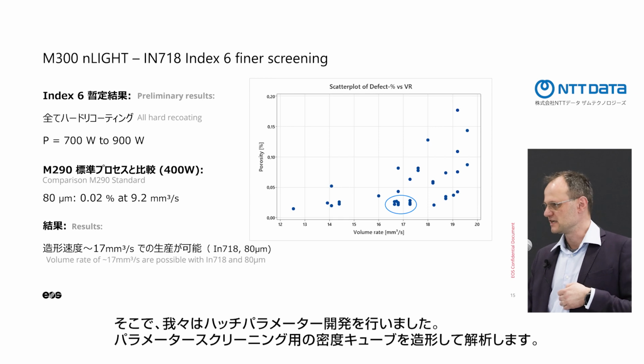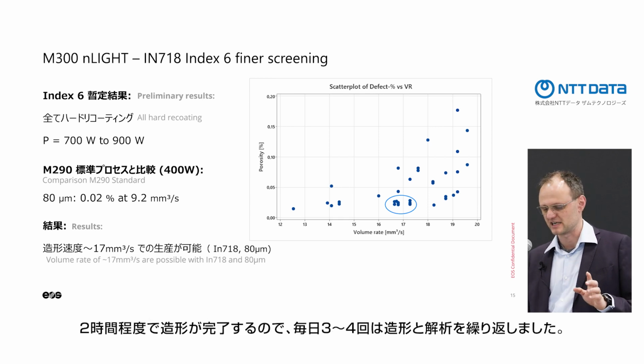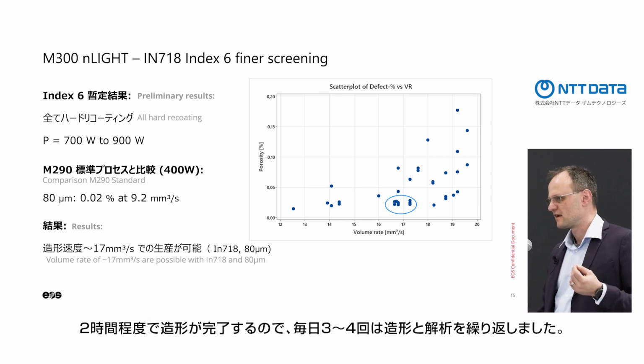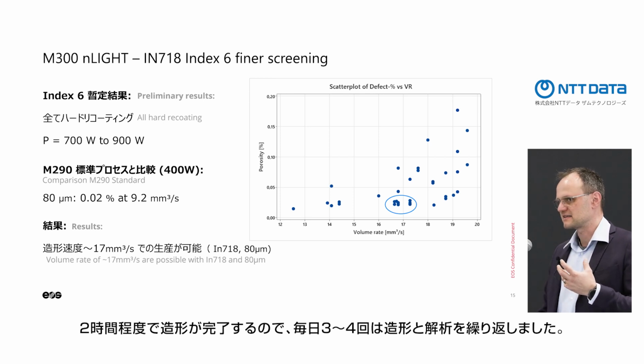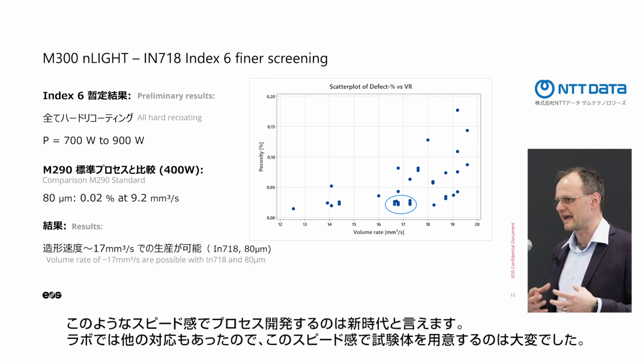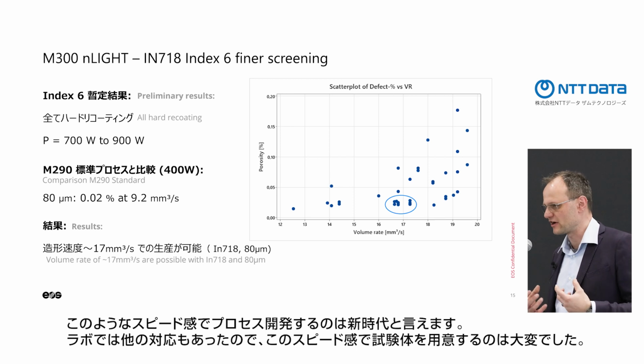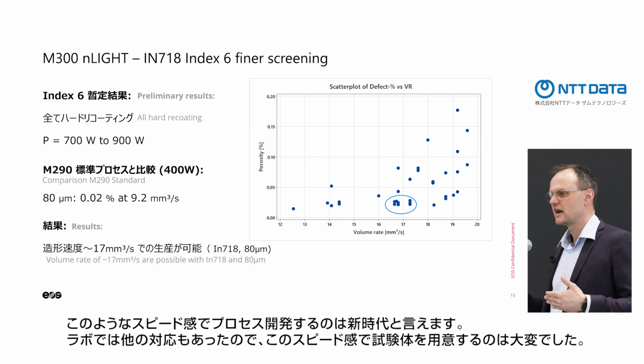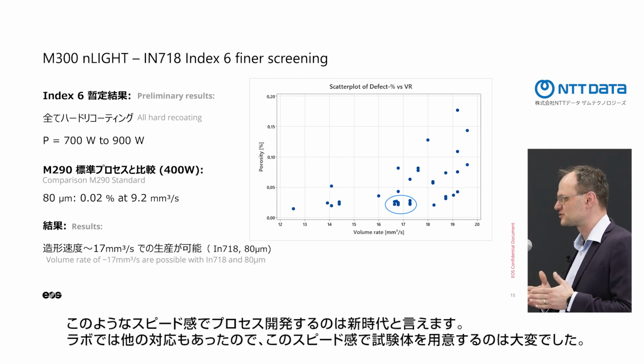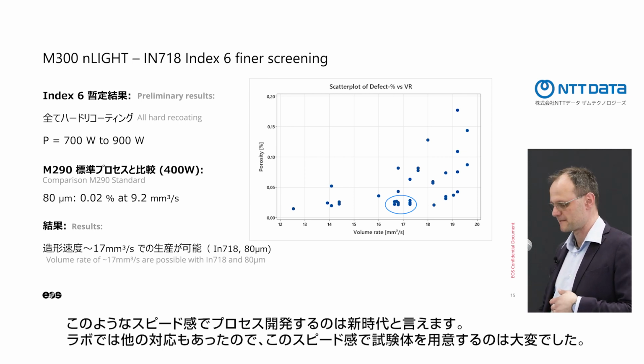And here our engineers got very interesting results because they ran 3 to 4 jobs every day with density cubes where they run parameter screenings, because the processes are so fast that a job runs only about 2 hours and then the job is already done and you can analyze it. So it was a whole new era for us to develop processes at a fast pace. Our laboratory was the bottleneck. Our laboratory was not fast enough to prepare all these samples because we were producing so many.